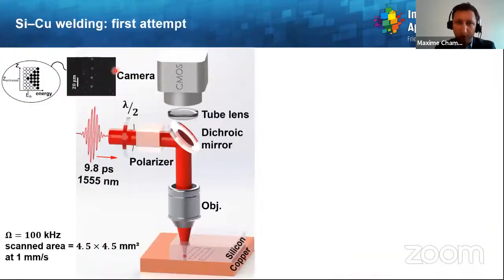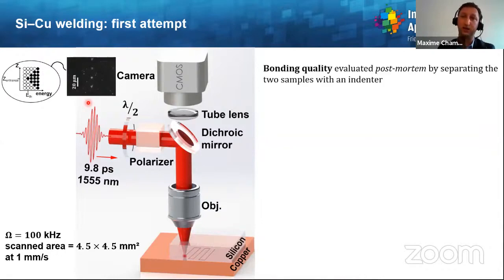To do so, we'll employ the following setup, which again relies on 1.55 micron wavelength and around 10 picosecond duration laser pulses. Then we adjust the energy classically with a half-wave plate and a polarizer before the beam is focused at the interface between silicon and copper by means of an objective lens. This objective lens is also part of a reflection microscope, which enables us again to position the geometrical focus with respect to the silicon entrance surface.